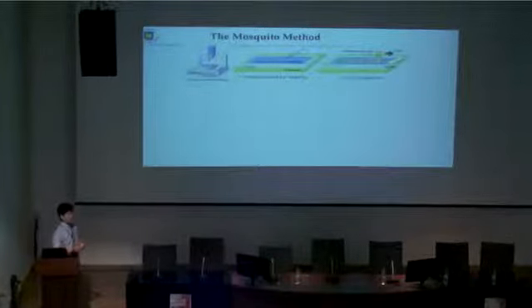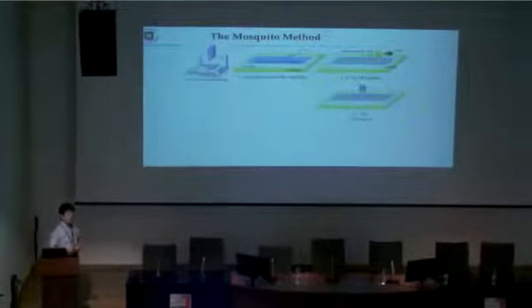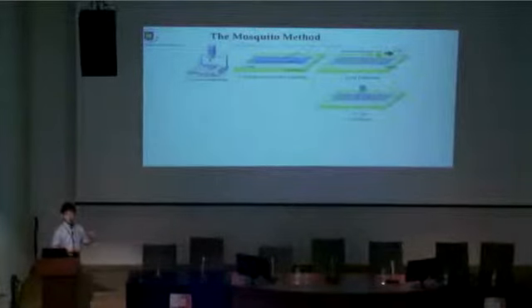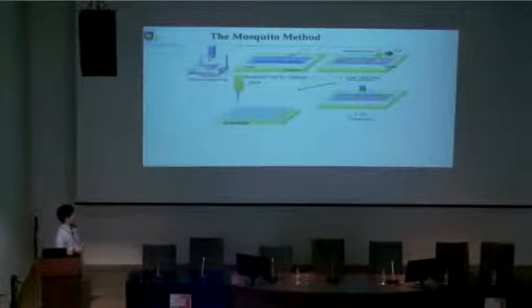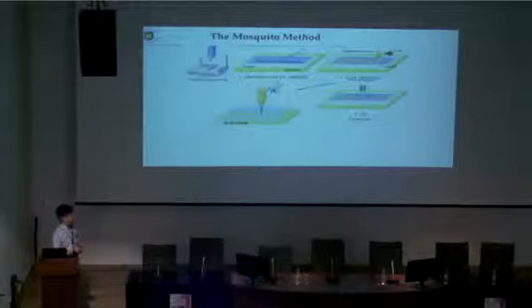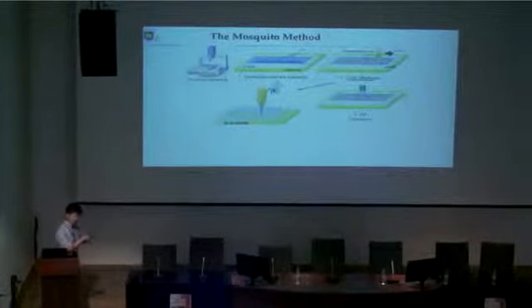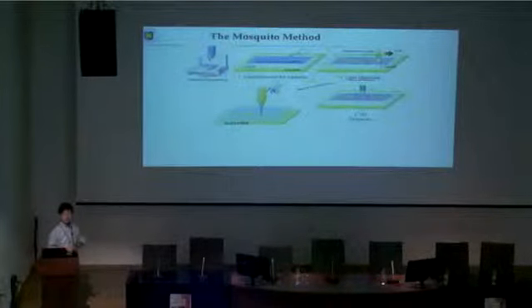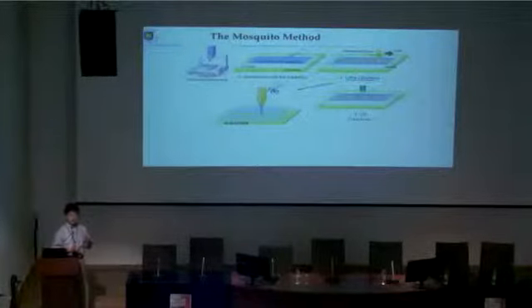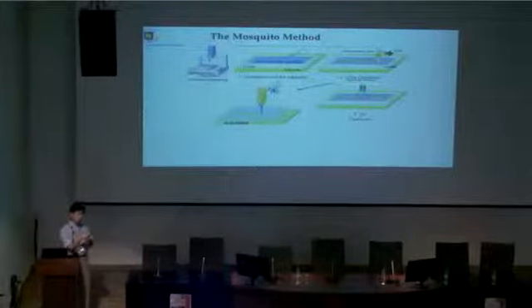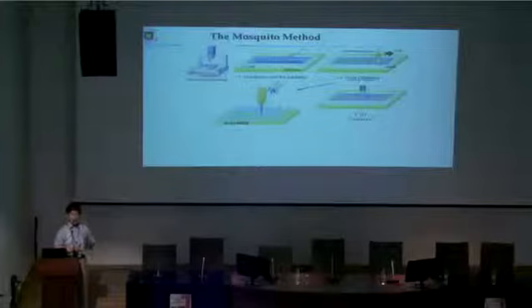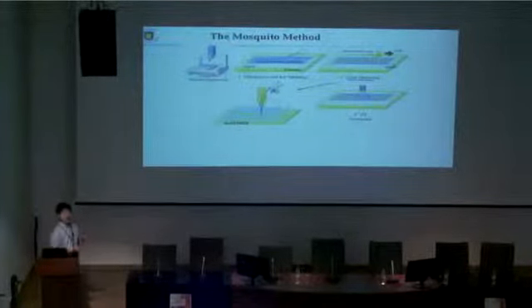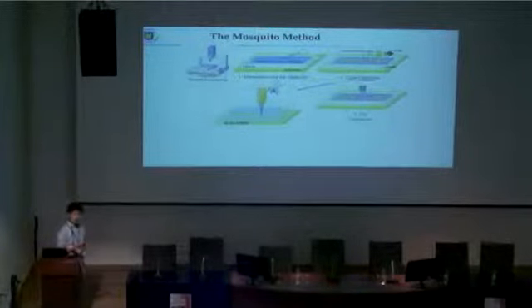Then a syringe that has a thin needle scans this way to write the core, parallel cores. And then after making this structure, just UV exposure for curing both core and cladding. Why is the name mosquito? Because the tip of the needle is injected into the cladding monomer like this way, not on the cladding monomer, but inside of the cladding liquid monomer. You can imagine why the toothpaste is maintaining its round shape on your toothbrush: because the toothpaste has high viscosity. We are applying that mechanism on this. High viscosity core monomer is injected into liquid monomer.